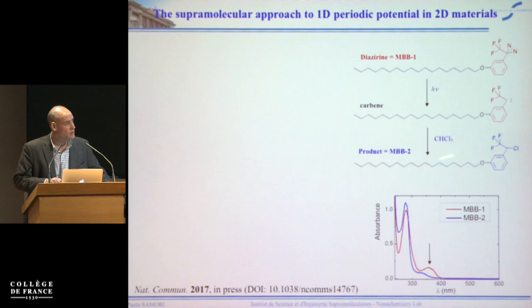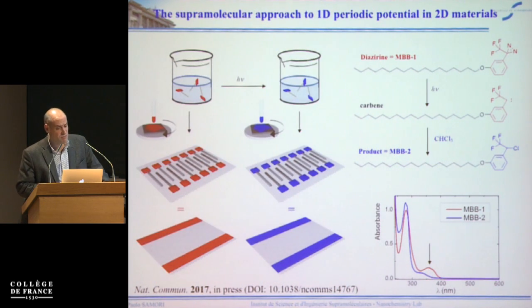And so you can see also photochemically that there is this kind of peak that is associated to the reactant that is reduced by formation of the product. Now, the idea here was very simple. It's an ex situ experiment. We start with either the diazirine or the diazirine that is irradiated in the beaker, so our product. We self-assemble them on the basal plane of graphene, dry the film by spin coating. And then actually we obtain this kind of order of some functional group. And these are the functional groups.